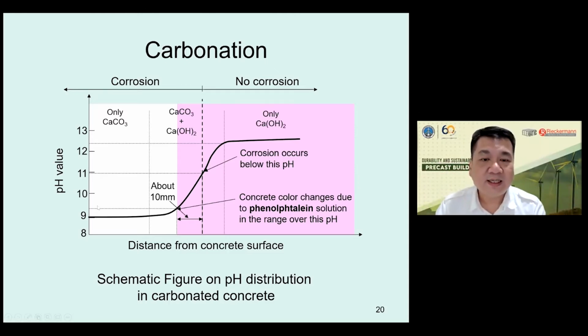And then the distance from the concrete surface, normally we call it the concrete cover. So when the pH is reduced, meaning the left part, when we have rebar on the left part, it will lose the protection of the passive film and can start to corrode. So this is the process of carbonation.